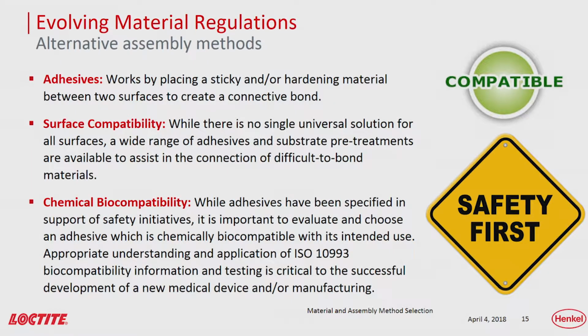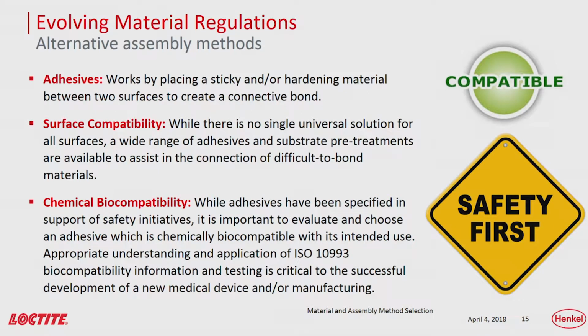Alternatives to solvent welding. As Jason mentioned, adhesives work very well as alternatives to solvent welds in that they place a sticky or a hardening material between two surfaces to create a connective bond. While there's no single universal solution for all surfaces, there's a wide range of adhesives and substrate pretreatments that are available to assist in the connection of difficult-to-bond materials, as Jason has mentioned. An interesting and important thing to note associated with any material selection, including the selection of adhesive, is that while adhesives have been specifically stated in support of safety initiatives, it's important to evaluate and choose adhesives which are chemically biocompatible with their intended use. Appropriately understanding and applying ISO 10993 biocompatibility information, both from your supplier as well as in your end use medical device, is critical to the successful development and manufacturing of a new medical device.